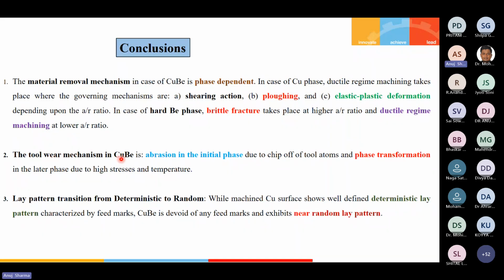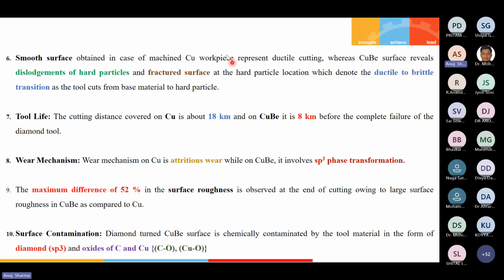And tool wear in copper beryllium: in the initial phases, there was microchipping, so abrasion was taking place, but in the later stages, phase transformation was dominant. As I said, a random lay pattern was observed on the copper beryllium surface, whereas a deterministic lay pattern was observed on the copper surface. Copper workpieces had smooth surfaces, whereas in copper beryllium there was dislodgement of hard particles or a fracture surface at the hard particle location.